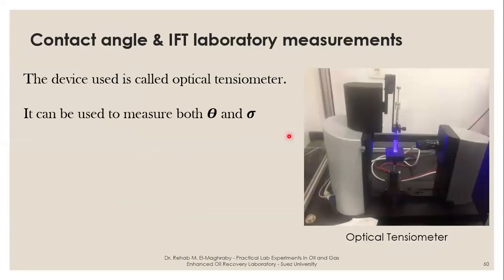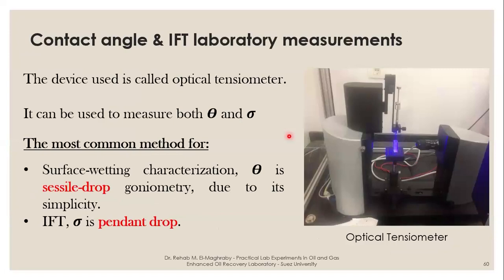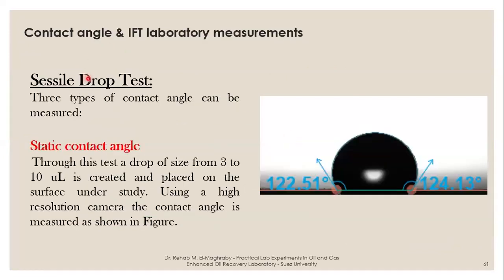We can do this experiment using a high pressure apparatus, or you can do this experiment at atmospheric pressure. For the contact angle, we use a test called the sessile drop test. For static contact angle, we just place a drop of oil, or in this case, a drop of water, and this is air, and this is the surface. So we find that there is a contact angle. We can measure the contact angle. This is a drop of oil. We have a drop of water, whatever the drop that we are using, it doesn't make any difference.